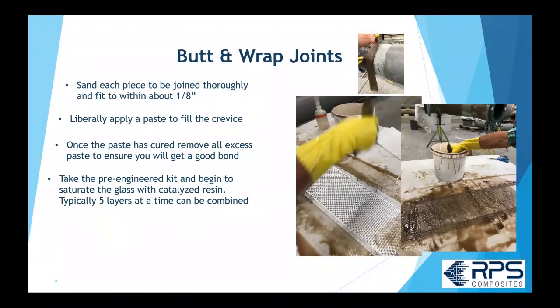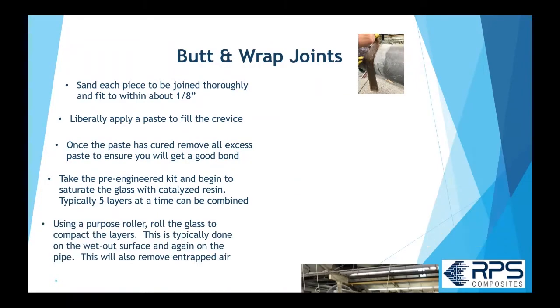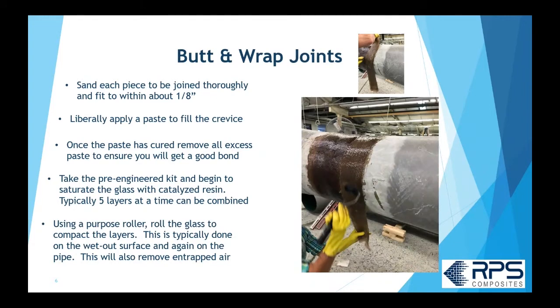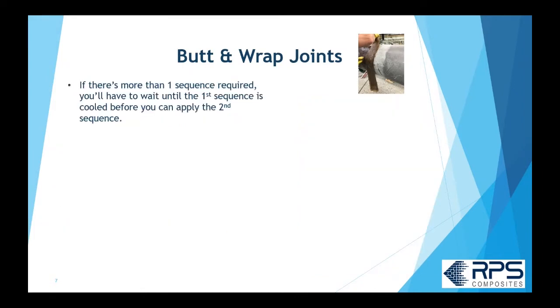And the next thing you do is you take a pre-made glass kit, you saturate that with catalyzed resin. You typically would apply five layers at a time, and you'd put that onto the pipe surface itself, and you'd use a laminating roller to compact the layers and roll out the air. And if you had another sequence, so for example, if your butt joint had 10 layers to put on, those first five layers are going to heat up. It's called an exothermic reaction, so you have to allow that to heat up and cure and cool down, and then you put on the next five layers, and you keep doing that until you have all the layers on that's required.